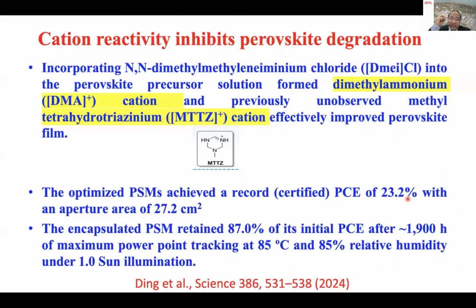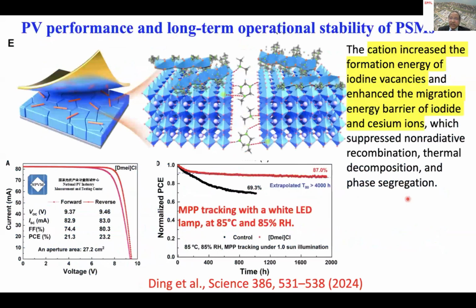Now, imagine what this new cation is doing. The next slide shows you what this cation is doing. When you have two crystals of perovskites, this cation goes in between the two crystals of the perovskite, and it binds to the halides through hydrogen bonding. So when you bind these protons to the halide iodide, you reduce the ion migration properties, and then the iodide vacancy formation is decreased significantly.